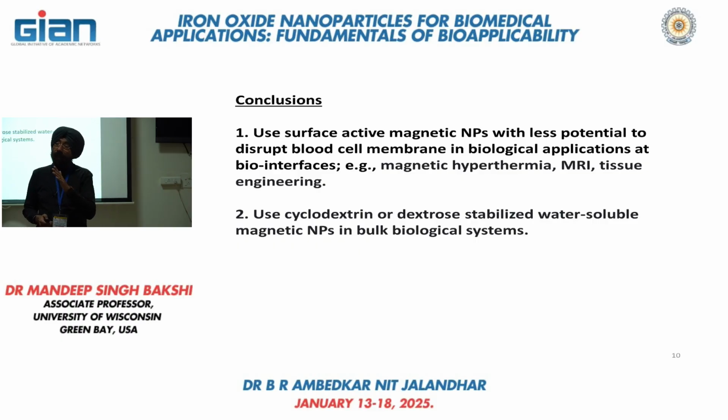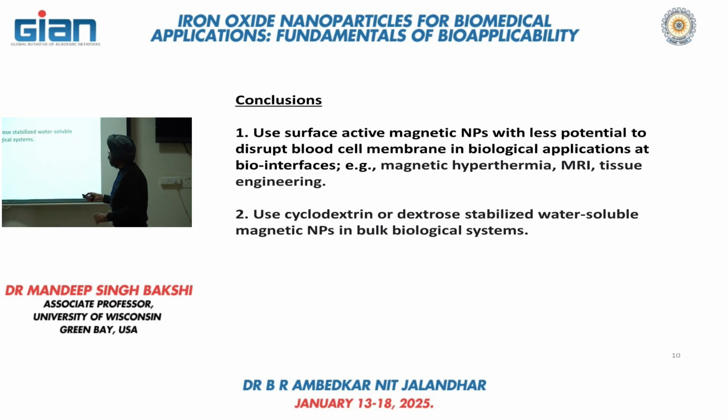So when you have to perform those kinds of experiments, you would prefer to use magnetic nanoparticle which are not breaking the blood cells. That is the meaning of that. Cyclodextrin and dextrose stabilized water-soluble magnetic nanoparticle are the best components of the water-soluble magnetic nanoparticle for bulk biological systems or the extraction of the blood cell from the whole blood.